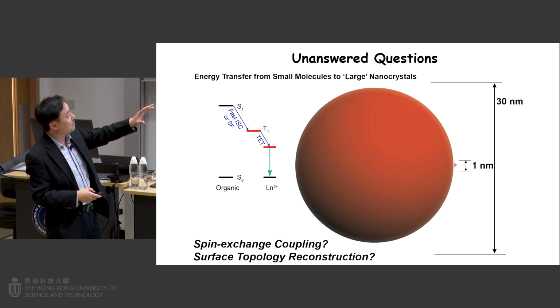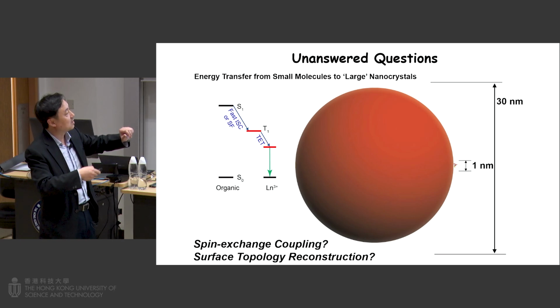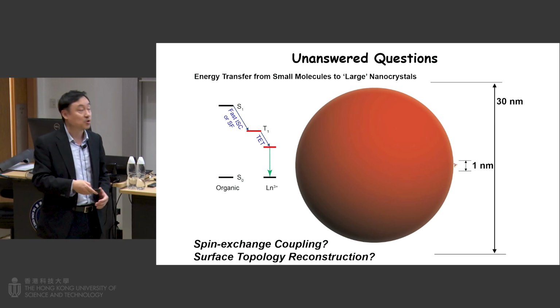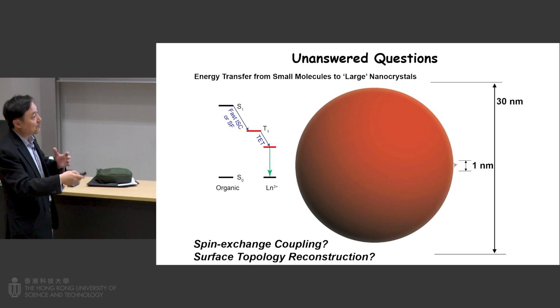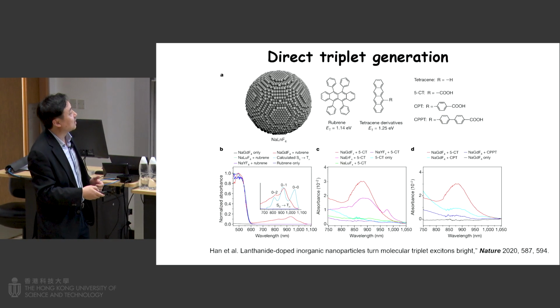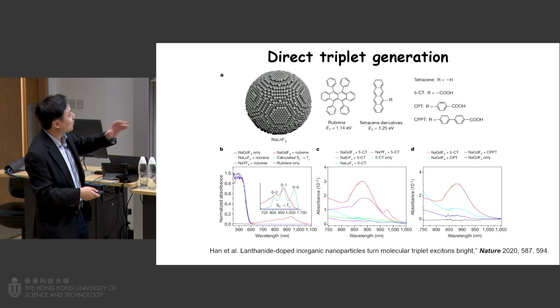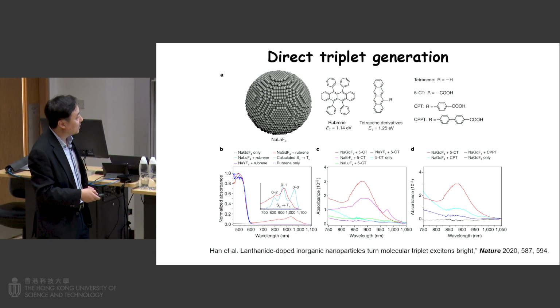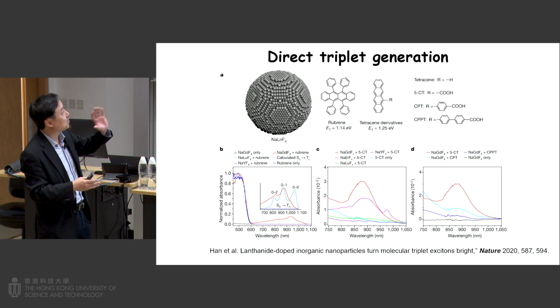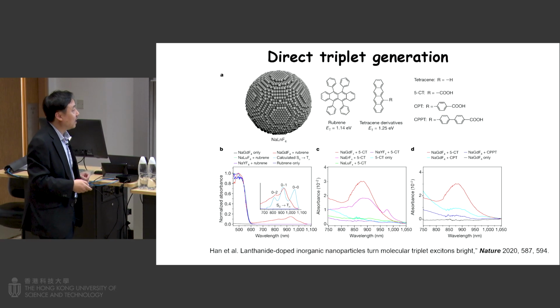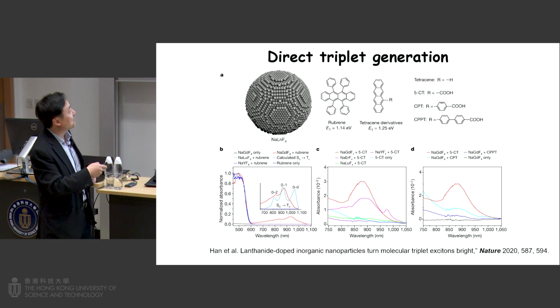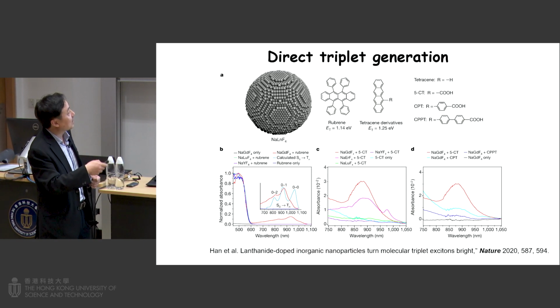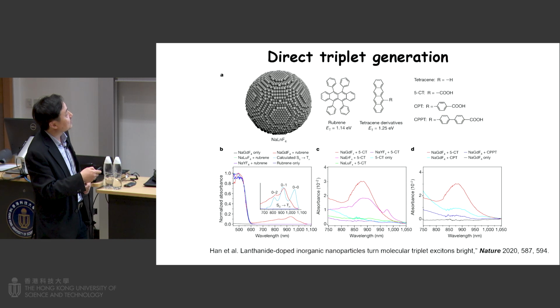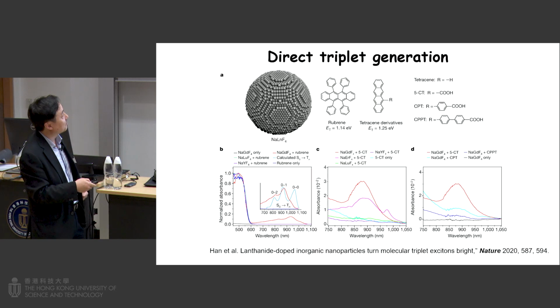Of course, another capability is that you can use the particles to study the triplet energy transfer process. You can study hybrid material systems. For example, a few years ago, I worked with Akshay's group from the University of Cambridge. We demonstrated that we can achieve direct triplet generation using hybrid materials, lanthanide-doped particles with these very popular organic highly conjugated molecules.